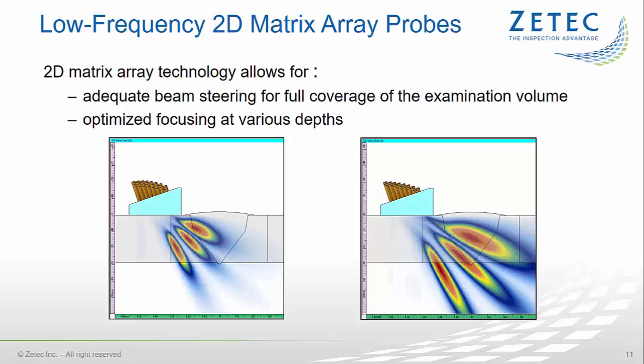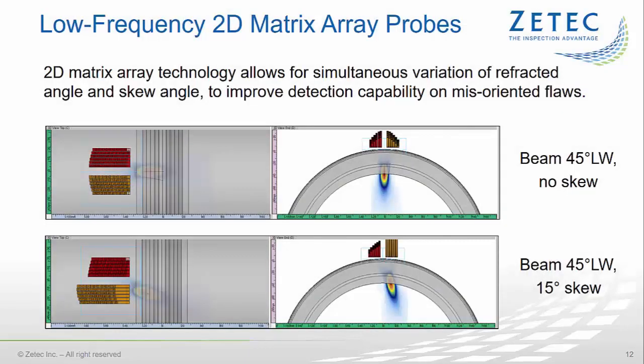The acoustic beam simulations on this slide, performed with the Ultravision Classic software, clearly illustrate these concepts. An additional benefit of 2D matrix array probes is that they can be used for simultaneous variation of the refracted angle and the skew angle of the probe. This can be used to improve the detection capability on misoriented flaws and also for increasing the inspection coverage. The acoustic beam simulations on this slide show beams at 45-degree L-waves generated with no skew and with 15-degree skew. We can observe that the shape and the intensity of the beams are very similar.